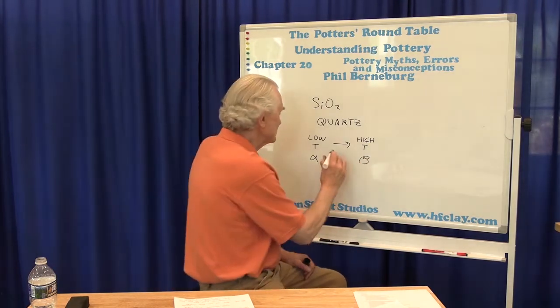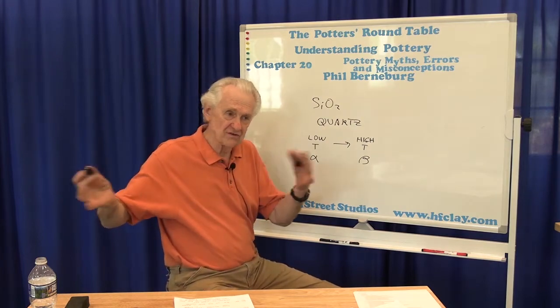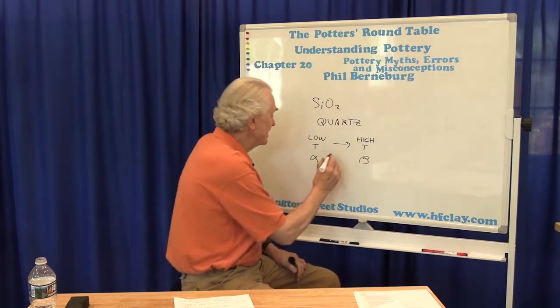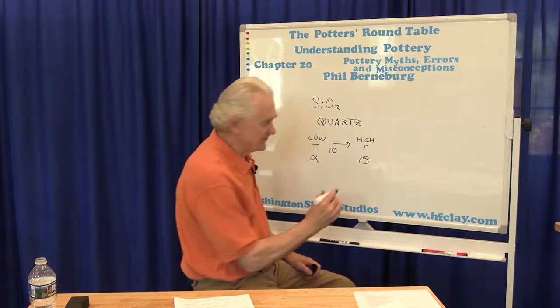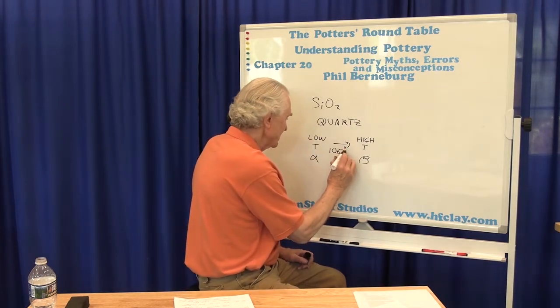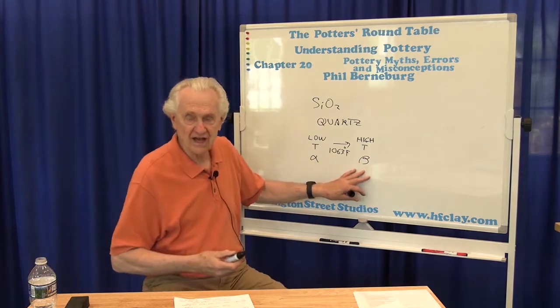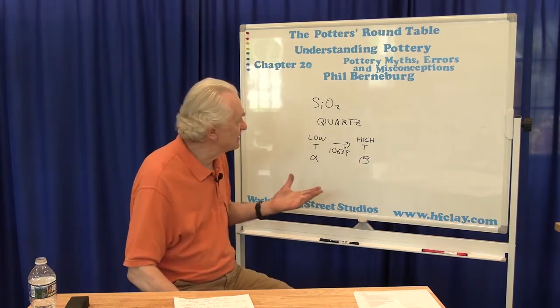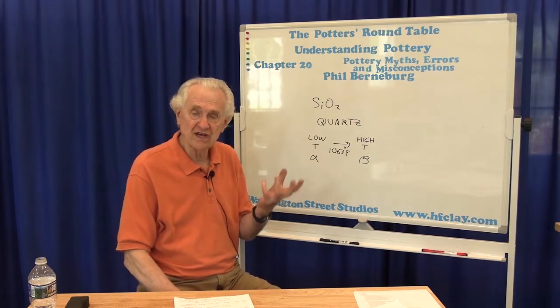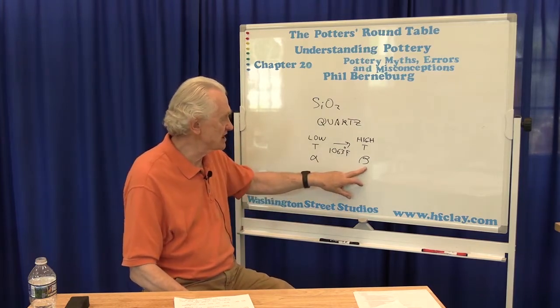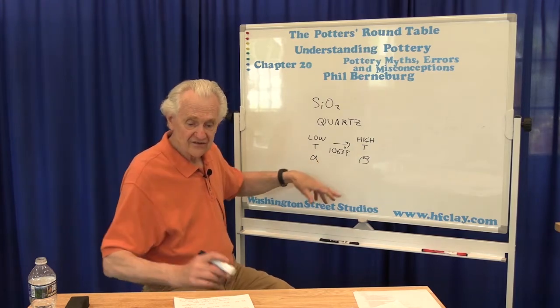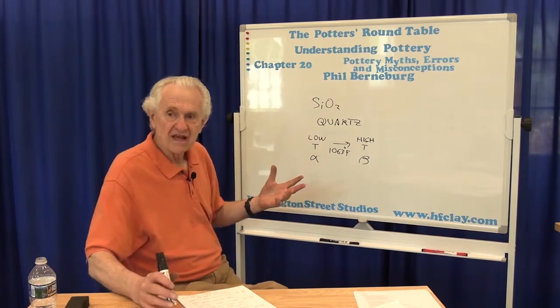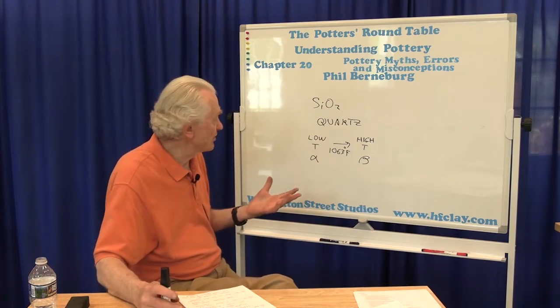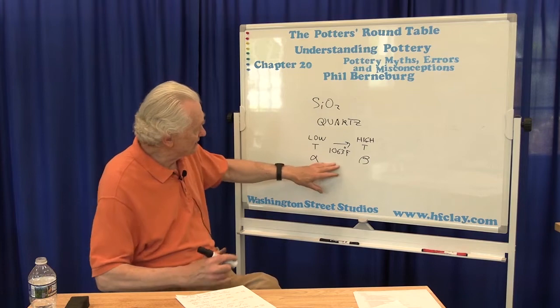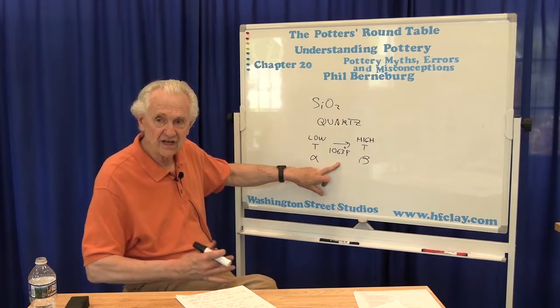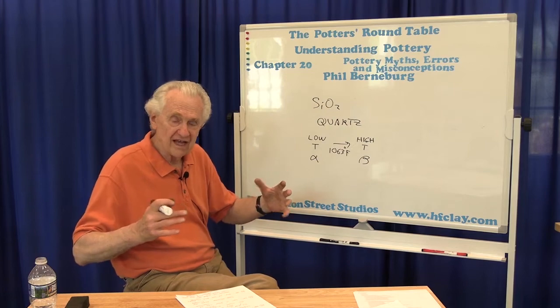If you take normal quartz that you find, for instance, out in your backyard, and it's very common, and you heat it up at around 1063 degrees Fahrenheit, it changes from the low temperature form to the high temperature form. If you had a chunk of quartz and you heated it up, there's nothing visually that you'd see, but internally, in terms of the atomic arrangement, it would change. And when it does that, it expands slightly. So the thought behind this belief is that since all clay basically contains some quartz, some more than others, if I heat up too quickly, when I get to around 1063, all the quartz in there is going to expand a little bit and crack the pot.